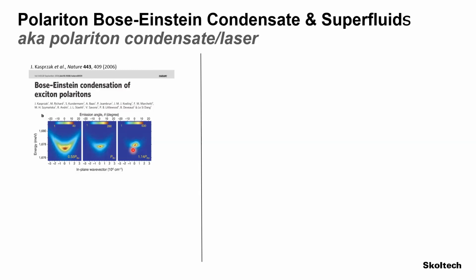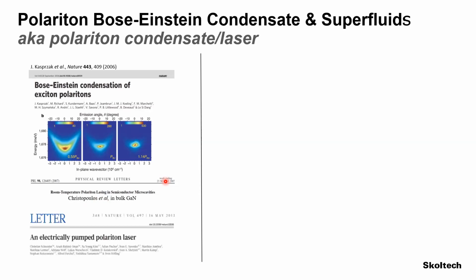Actually, with my very first PhD student in 2007, we demonstrated polariton lasing at room temperature in a bulk gallium nitride microcavity. And then in 2013, a group from Würzburg, the group of Sven Höfling, demonstrated that you can use the fact that you are dealing with semiconductor nanostructures and you can inject carriers electrically and create the first electrically pumped polariton laser.